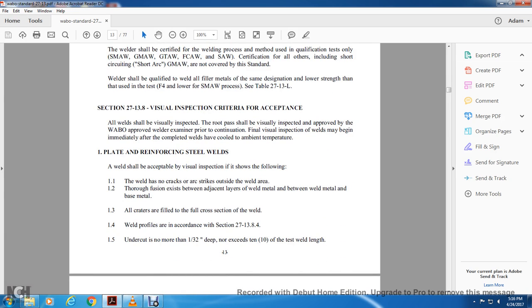Alright, Section 27-13.8, the visual inspection criteria and acceptance. All welds shall be visually inspected. The root pass shall be visually inspected and approved by the WABO welding examiner. Final visual inspection of welds begins immediately with completed welds that have cooled to ambient temperature. 1. Plate reinforcement steel welds. The weld shall be acceptable by visual inspection showing the following. The welds have no cracks or arc strikes outside of the welded area. Fusion exists between adjacent layers of the weld metal and between the weld metal and the base metal. All craters are filled to the full cross-section of the weld. The weld profiles are in accordance with Section 27-13.8.4.